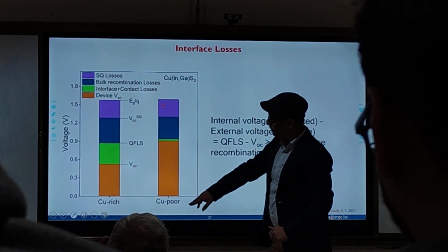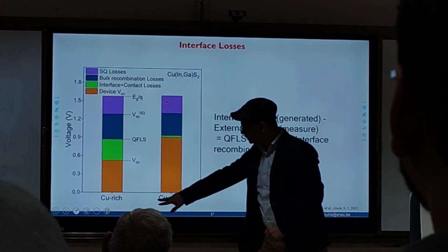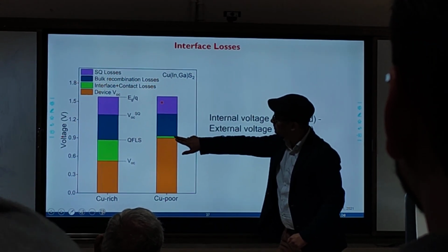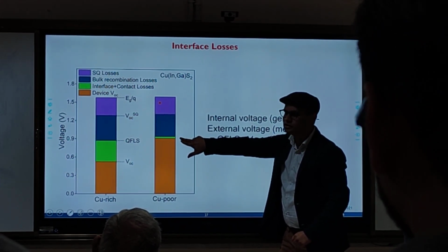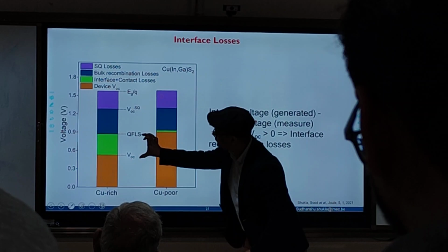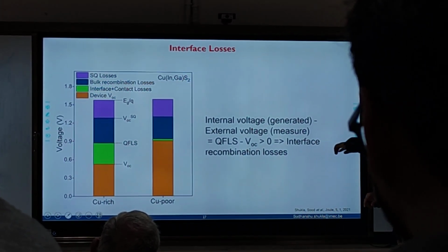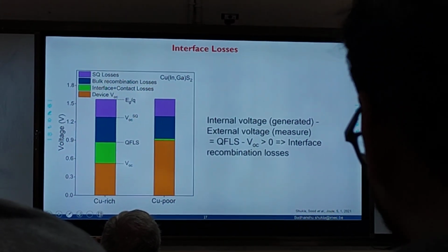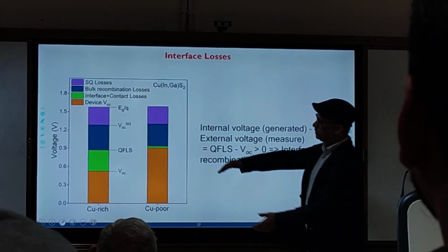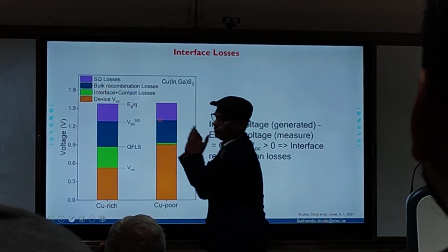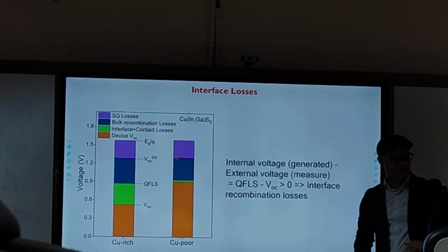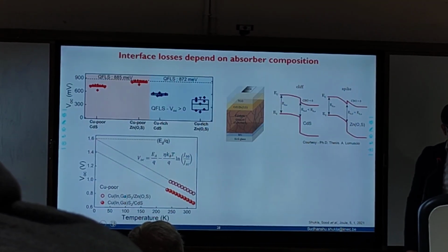Okay, so what we did, this is the case of copper rich, but in the case of copper poor, you see this green thing is substantially suppressed because the difference between QFLS and VOC, which is here, is nothing but the interface recombination. Okay, this is material quality loss, this is the interface loss. You want to suppress it. And how did we manage to suppress it?